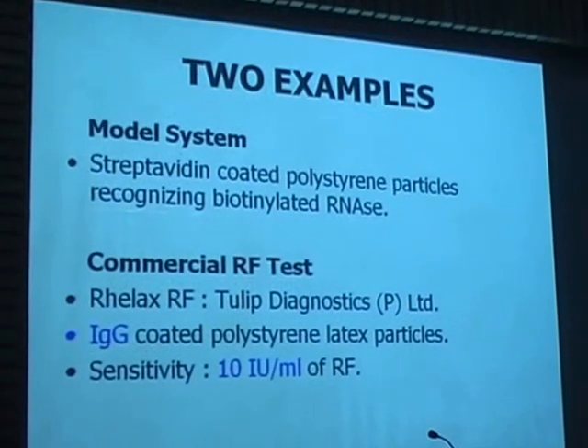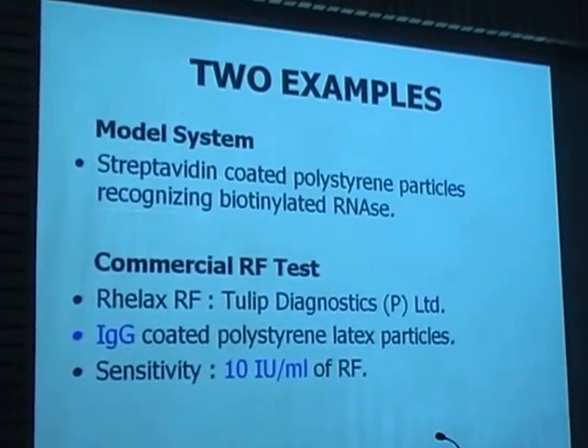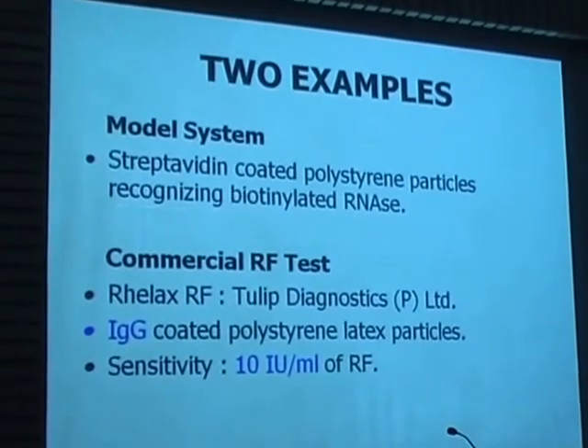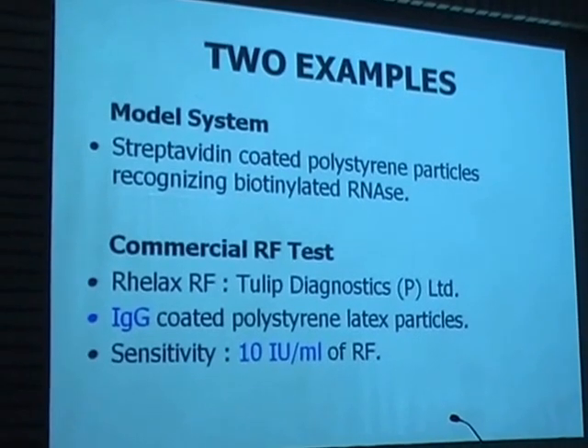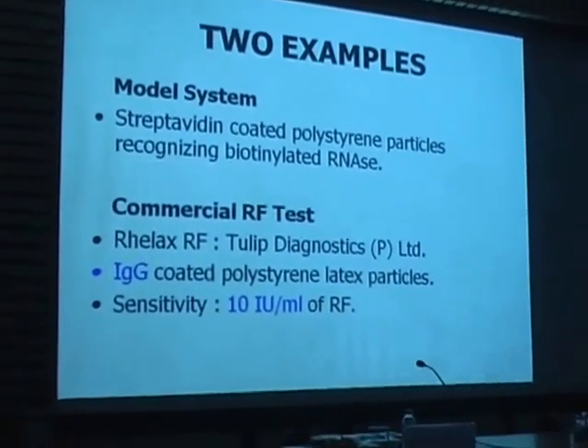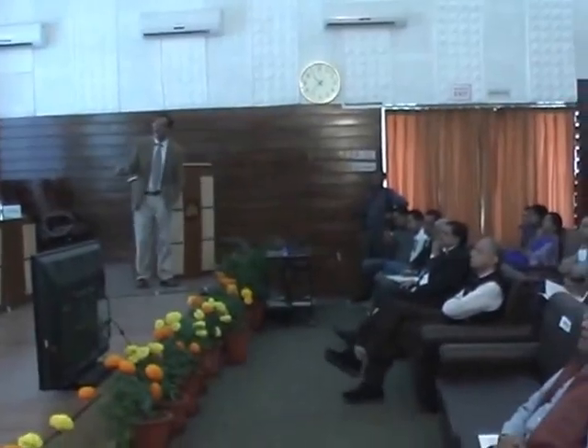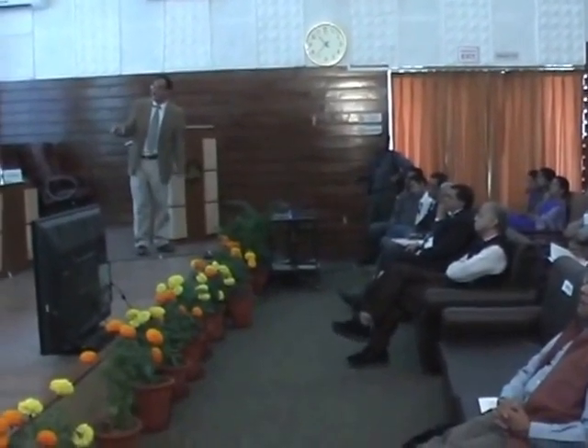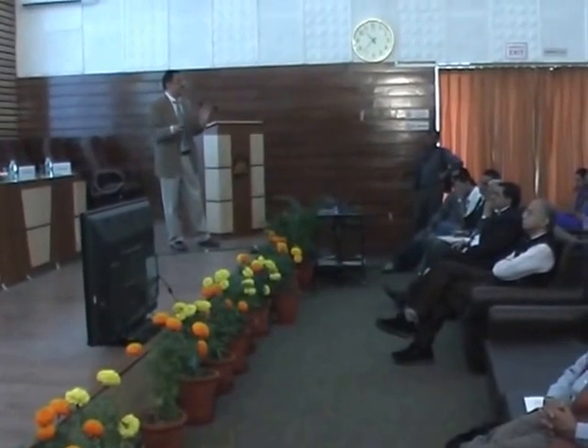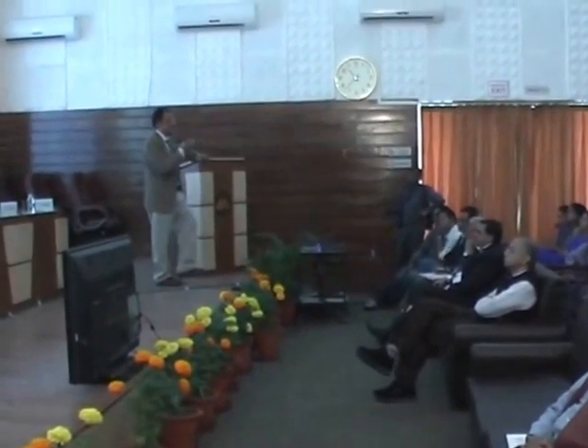We tested this idea with a very simple example. We took colloidal particles with streptavidin and we took RNase, and attached biotin to this, and we tested how much of the RNAs we can detect by this method. And the second one is a commercial test which we did. So here we show that when we do this test without the electric field, we need about 1 micromolar per liter of antigen, RNAs. But now if we put this electric field, from these images we showed, even at 10 picomolar, we have huge sensitivity and very, very fast detection. So it has enhanced the sensitivity tens of times for this diagnostic.